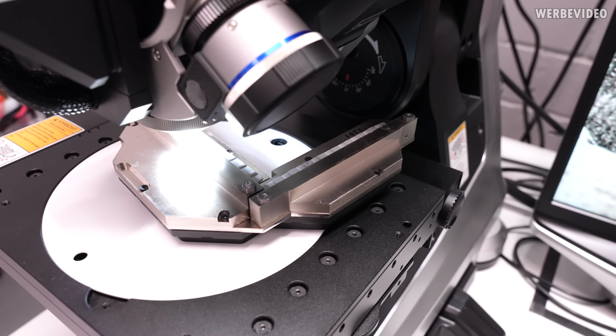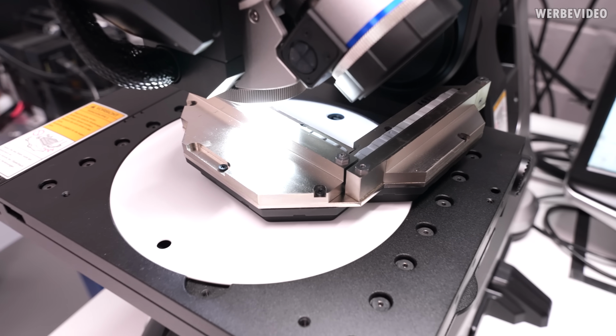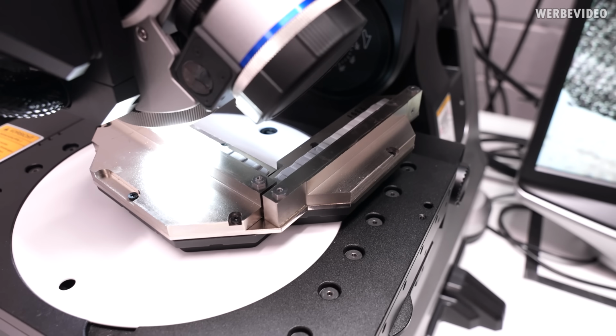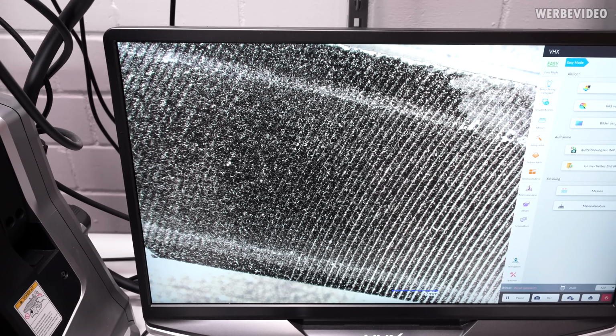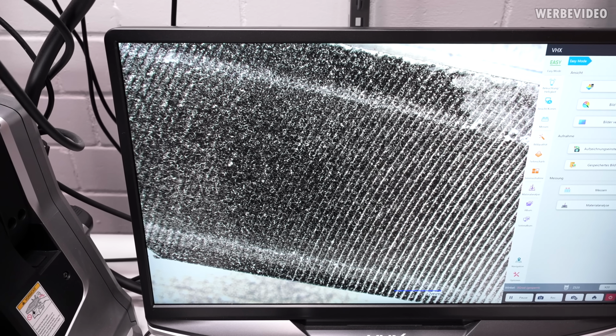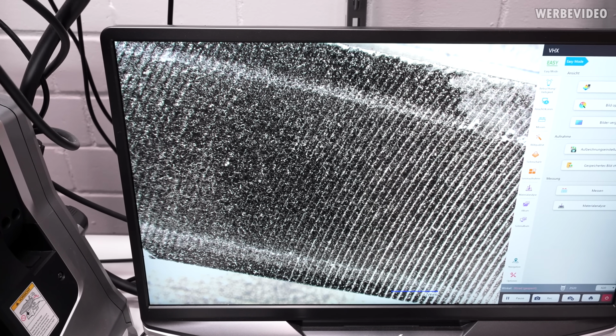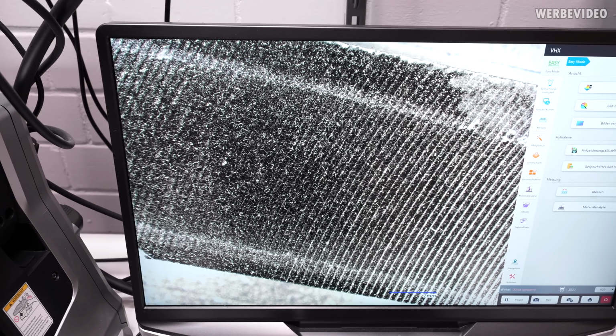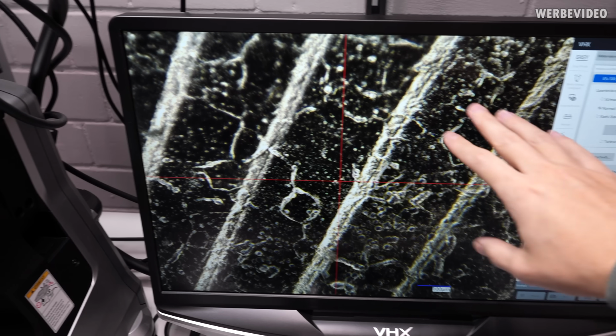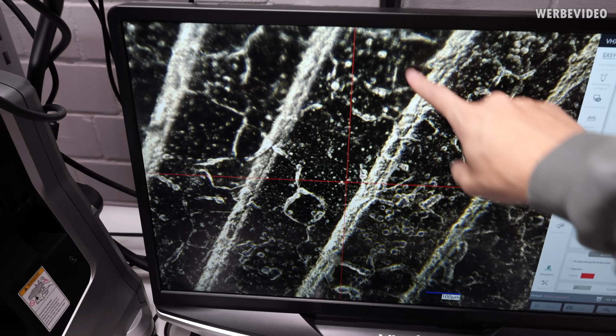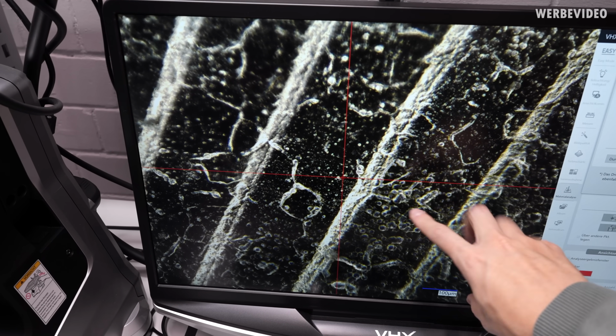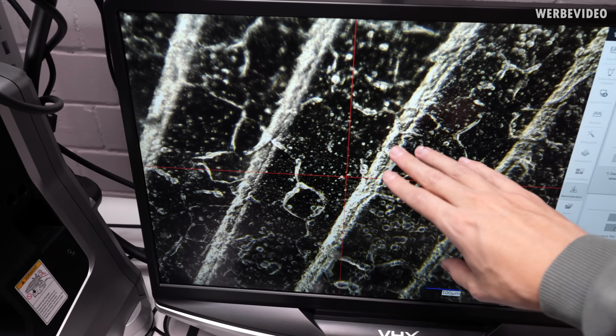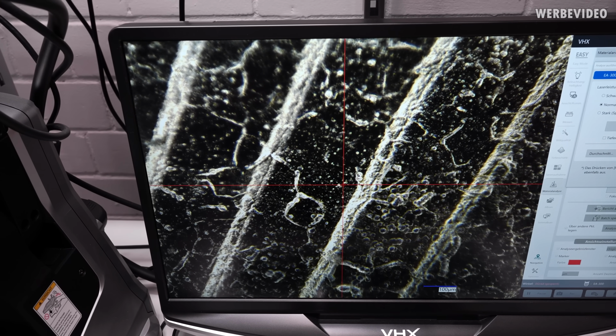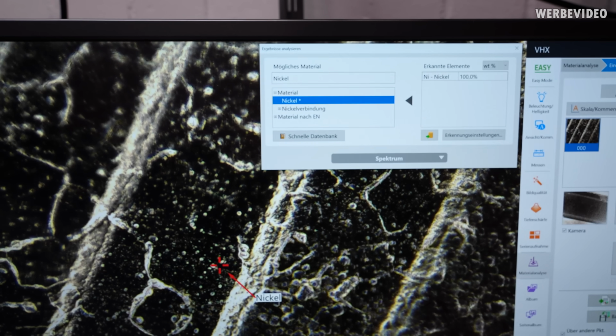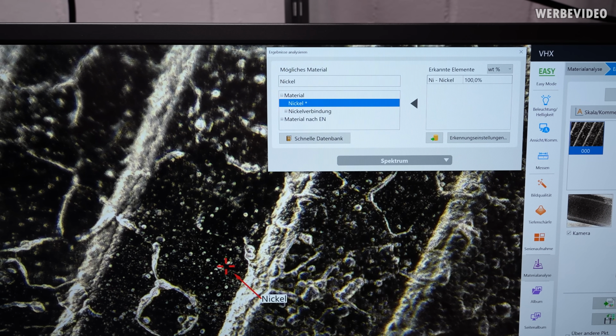First of all, we're looking at the material of the contact area that is making direct contact with the thermal pads. That's under the microscope, 20 times magnified. You can see all those grooves from the milling process, and we're now changing to the material analysis unit. So that is the same thing, just 300 times magnified. Those are still the grooves from the milling. And on top, we have some kind of coating. It's probably nickel coating. And that's what we want to analyze. So the top layer is definitely nickel. We can see 100% nickel coating.